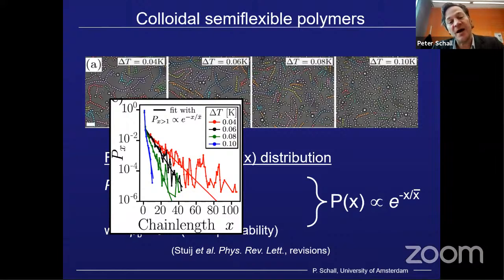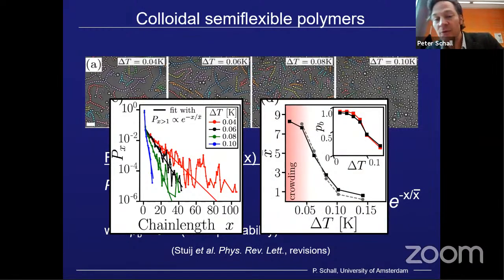So here, plotting in a half logarithmic scaling, I'm plotting these length distributions, and you can see as we get stronger and stronger attractions, we get longer and longer chains. So initially, very short chains, the green one has longer ones, even longer ones. And in fact, you can use this average chain length to back out the bonding probability, compare it with the measurement I showed before of the average bond lifetime, and you find a really good consistency. So that shows, in a nice model, that this polymer equilibrium theory really works for these particles.